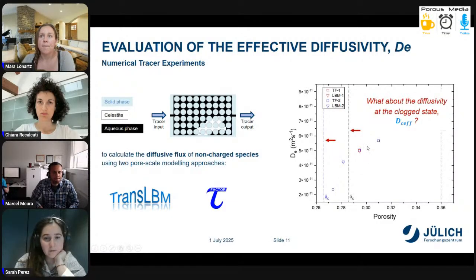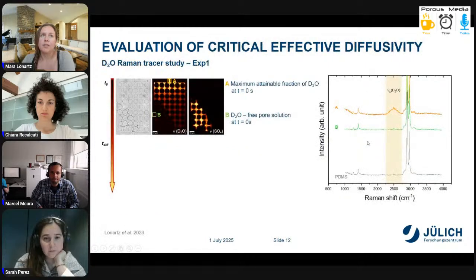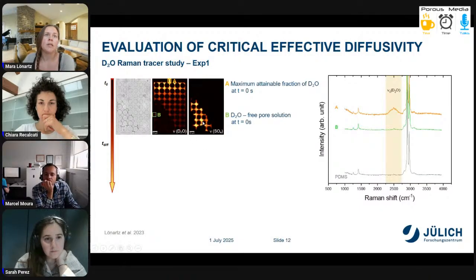For this, I conducted Raman isotopic tracer experiments. As soon as the chamber was clogged, I injected the strontium chloride dissolved in pure deuterium. What we can see here on the left side is the integrated intensity signal of the Raman modes representative for deuterium, and we can see how deuterium is diffusing into the chamber. Here we can see the intensity of the symmetric stretching mode of the sulfate. So that's the distribution of celestine.